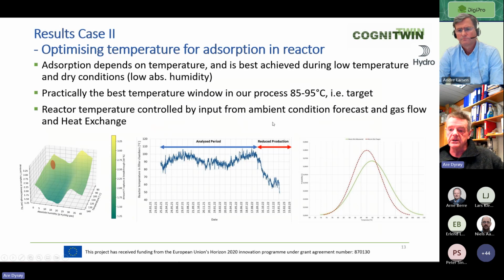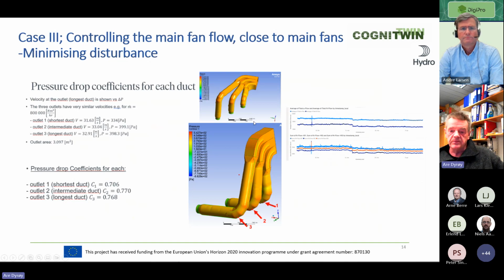We also developed prior to this, but also further developed within the system, a cheap way to measure high or large duct gas flow by the use of ordinary DP cells, delta pressure cells, combined with simulation in CFD, where we get the constants for the system. And then we had the gas flow control in order to control the main fans, but also as a feedback to the model of how much gas with which concentration gave us the amount of fluoride that we needed to meet with secondary aluminum.